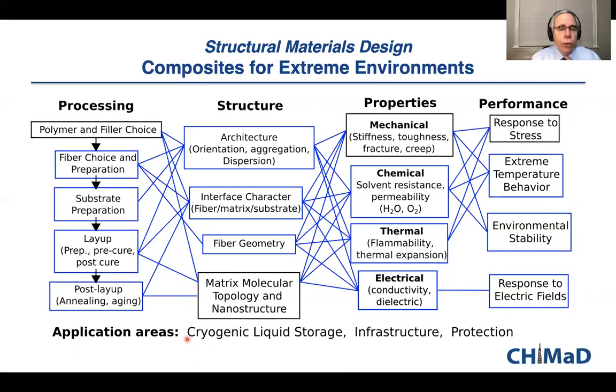And the idea is to choose a polymer and fillers, and by this processing, the layup process, alter the structure, to give you the mechanical properties you need, such as the stress, the ability to withstand extreme low temperature behavior associated with cryogenic storage, and a response to, for example, electric fields. This is important when you use these in applications, for example, in aerospace.